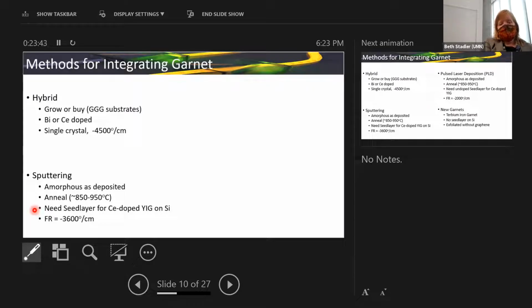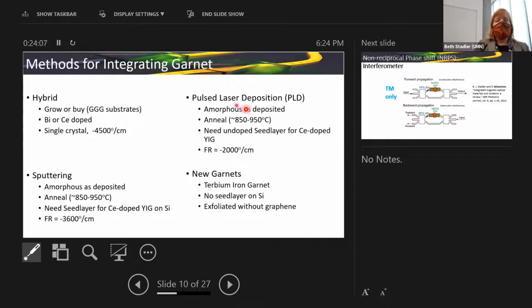That was actually an interesting study where Carolyn Ross's group at MIT took the method we had figured out to put garnet onto silicon and said, if we do that with undoped material and anneal it like Beth did in Minnesota, then put doped garnet on top of that and anneal it again. I'll discuss that in a minute, but they used pulse laser deposition instead of sputtering.